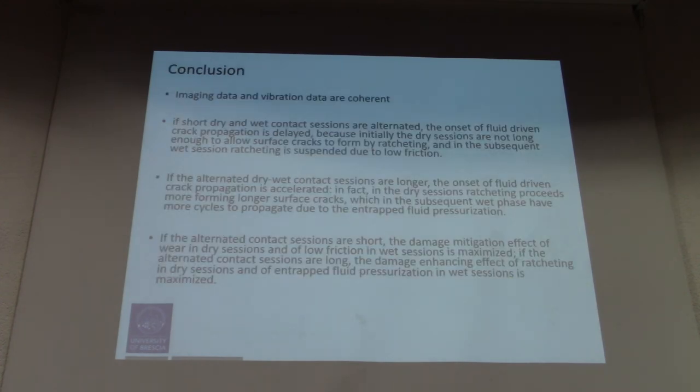This is because when the duration is longer, the ratcheting can propagate during the dry phases. And then when the lubricant can penetrate into the cracks, the combination between wear and fatigue phenomena is more destructive than what happens when the duration length of the dry and wet phases is shorter.